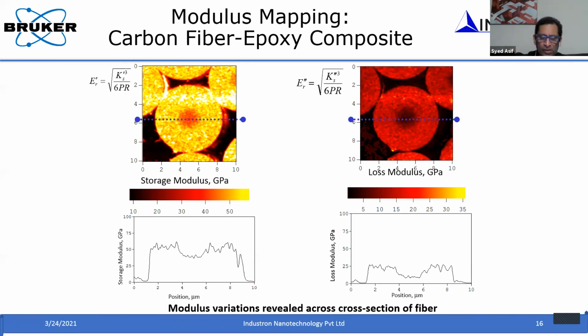So then we have a powerful way of looking at the data and taking the cross-section at any point. For example, I've given the cross-section image of the storage modulus for this fiber epoxy composite. You can do that for loss and storage modulus. So it's a very powerful technique. You can simply implement it on any polymer surface. You do have to have a very nice smooth surface, because roughness may affect your stiffness measurement.